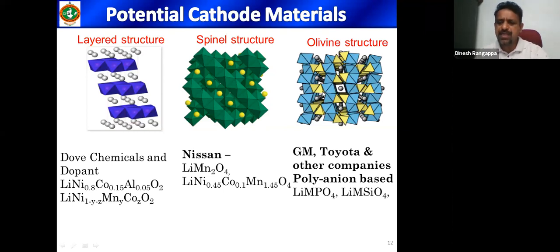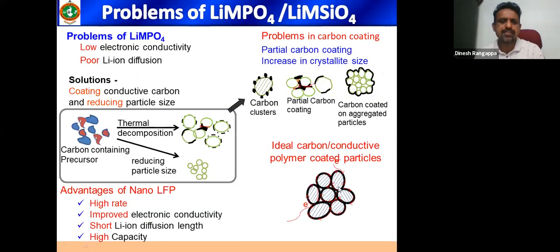And the olivine-based material is a safer and more stable material, and also cheaper compared to the layered and spinel structures, because cobalt is not involved in this. It is mainly based on lithium iron phosphate and lithium manganese phosphate. Lithium metal silicate with two lithium is also expected, but this material is still facing some problems and is under development. But olivine-based lithium iron phosphate has already got commercial production and application in commercial batteries.